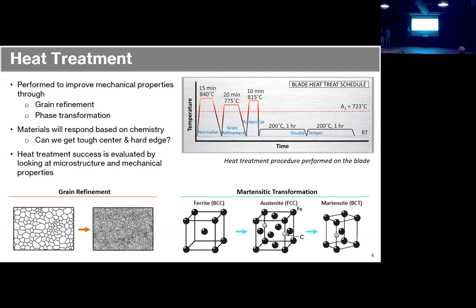The other thing that happens when we go above this line is we're actually transforming this ferrite, this BCC phase, to this austenitic phase. And as you can see here, more carbon is able to solubilize into the microstructure in this austenite phase. So when we get it up here and then we're going to quench it, so that's just a really fast cool, what happens is this material actually wants to go back to this structure when it comes back down to this temperature, but because we cool it so quickly, we trap it in this intermediate phase called martensite, and you can see that a lot of the carbon is still there.